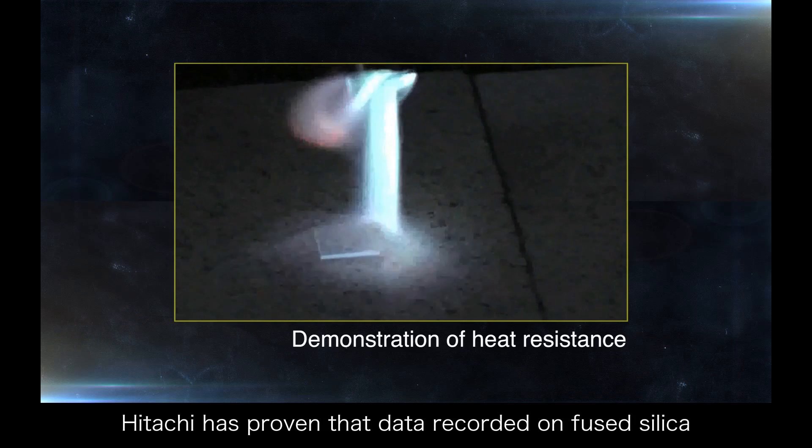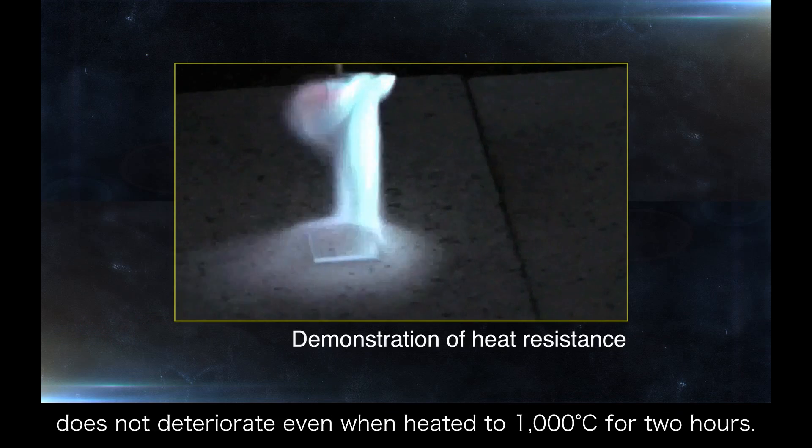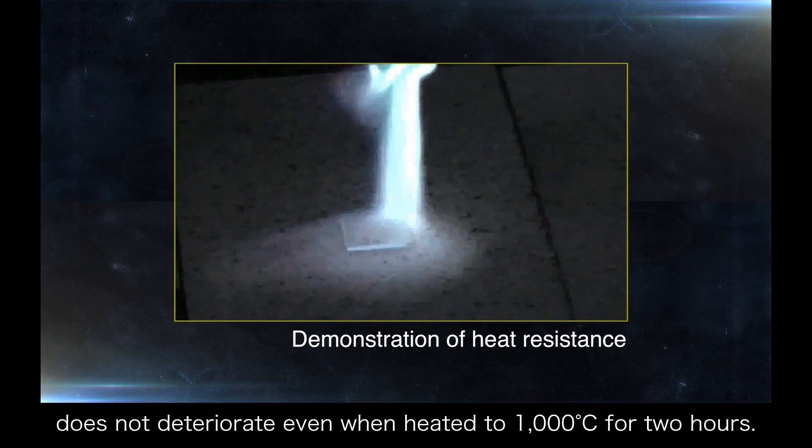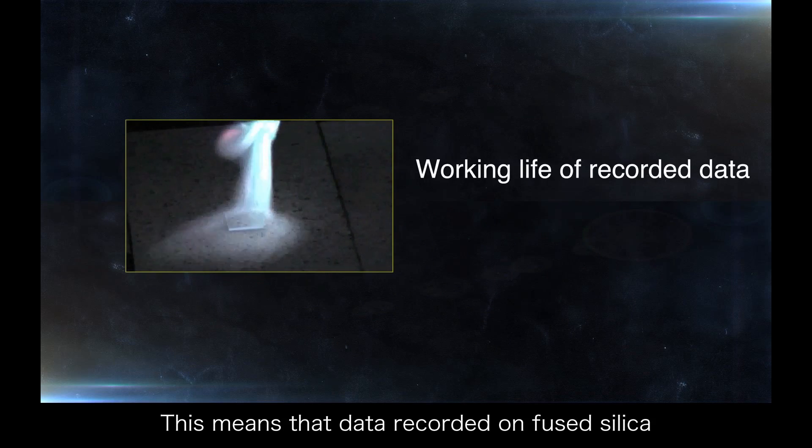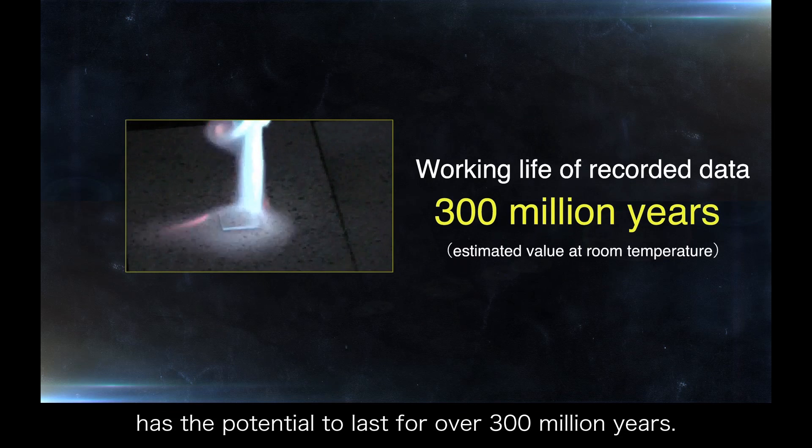Hitachi has proven that data recorded on fused silica does not deteriorate even when heated to 1000 degrees Celsius for 2 hours. This means that data recorded on fused silica has the potential to last for over 300 million years.